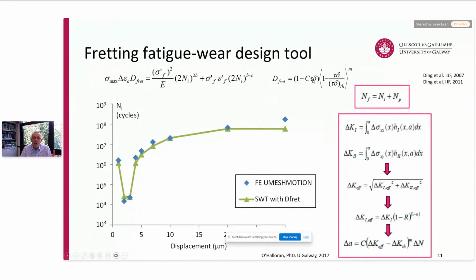And that approach basically allows us to, there are two approaches here. You can do a time-consuming finite element U-mesh motion, the blue dots here, where we can see how the crack initiation life varies with this applied tangential stroke. And we can see there's a reduction in life with increasing stroke initially due to partial slip and transition to gross slip, and then an increase in life and a leveling off of life with further increasing stroke, pushing up into the gross slip regime. And that's a time-consuming approach, the blue dots, if you use a finite element model with the incremental cycle counting approach that I mentioned earlier. But what we're saying is that you can replace that by this fretting damage parameter, and that's much more efficient. You really just need to do one finite element analysis. You don't need to simulate a cycle counting type approach.